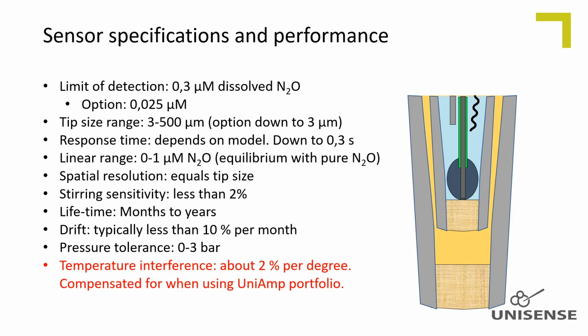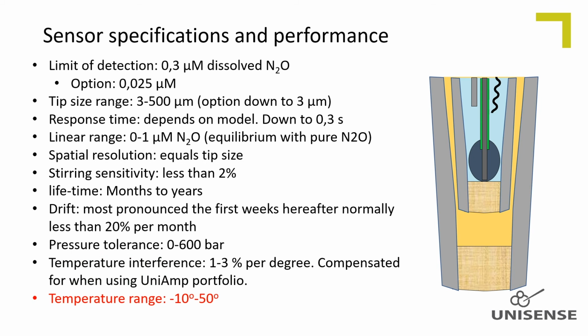In the web lecture about amperometric microsensors, the temperature influence is discussed in detail, and it is explained why temperature compensation is difficult for amperometric microsensors. The temperature interference is about 2% per degree. For sensors used with the new UniAmp portfolio, temperature is compensated for within a plus/minus 3 degrees Celsius interval. The sensors can be used from minus 10 to 50 degrees Celsius. At higher temperatures, the baseline and noise level increase and compromise the sensitivity.